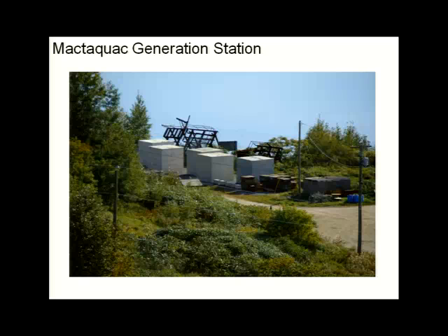So they anticipate using the fly ash that's coming from the coal-burning power plant that's very close to this dam. But they've had the foresight that if the fly ash is no longer available, or if that coal plant closes down, they've actually reserved a section of fly ash set aside specifically to have enough to reconstruct this entire dam project in about 15 years. So it's a pretty extensive study that's gone on to actually make sure that we're not going to have any problems with ASR. So we're monitoring this now.